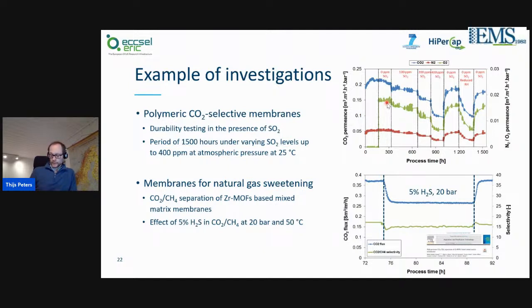Another work topic that we have worked a lot with is CO2 methane separation. So membranes relevant for natural gas sweetening, where we have tested the effect of not only trace levels of H2S, but up to very high concentrations of H2S, in this case 5% of H2S in a mixed CO2 methane synthetic natural gas at 20 bar and 50 degrees to see the effect of the contaminant on the membrane performance.